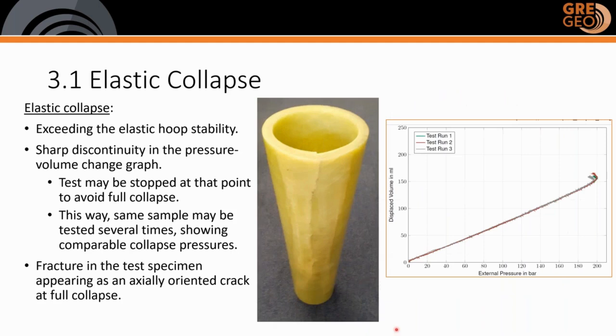In this next slide, you see a typical elastic collapse pipe, or a pipe that has been subjected to an external pressure and failed in elastic collapse. This is one of the pipes we tested that exceeded the elastic hoop stability criterion until full collapse. The instability point is characterized by a sharp discontinuity in the pressure versus volume change recording during the test, as indicated in the plot you see here.